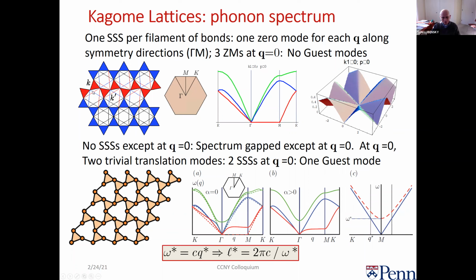And by the theorem that the number of states of self-stress equals the number of zero modes, we have to have a zero mode for each line. This shows a depiction of what the zero mode from the straight line going down here is. So when I calculate the phonon spectrum, I'd better have a number of zero modes proportional to the number of straight lines, which is basically related to the perimeter of the system, because I have a zero mode for each line going like this and each line going the other way. Sure enough, when I calculate the spectrum of the system going from gamma to M, I have this zero mode going from gamma to M here.